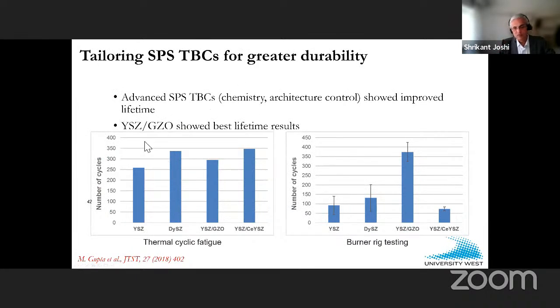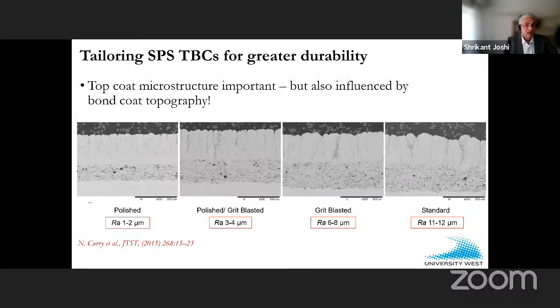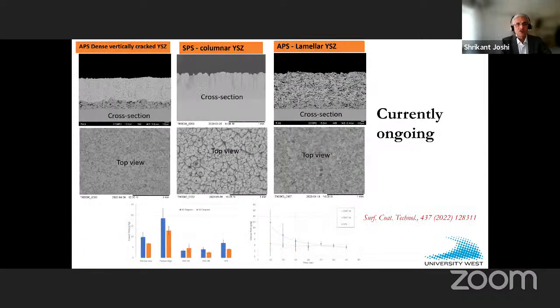Yeah, and we've been kind of, to close the loop, looking at not just microstructures, but how the coatings perform in thermal cycling situations, in burner rigs. The other interesting area has been to look at bond coat topography and the influence on coating microstructure and lifetime. So this is some of the work that looks at different pre-coating surface treatment on the bond coat, pre-coating of zirconia, I mean. And as you see, you get remarkable differences in column density that influences coating life, right?